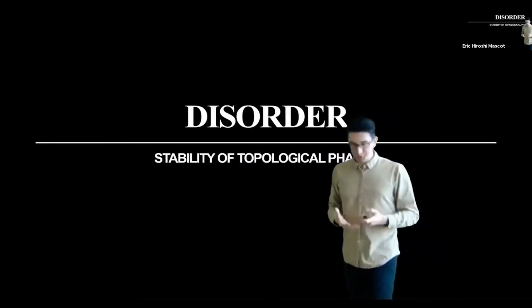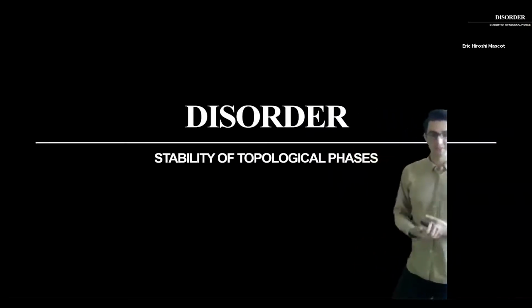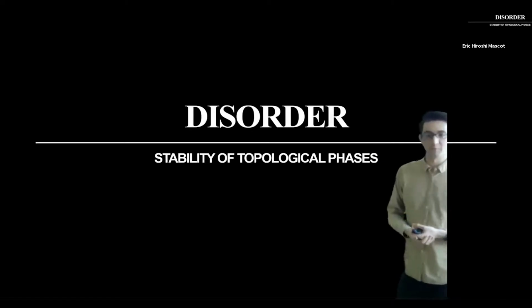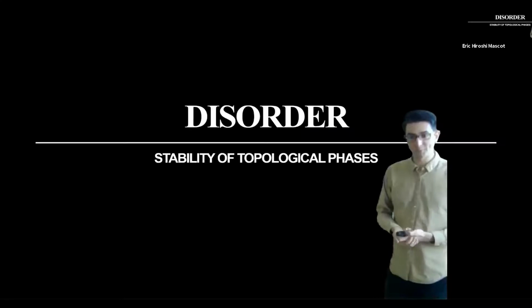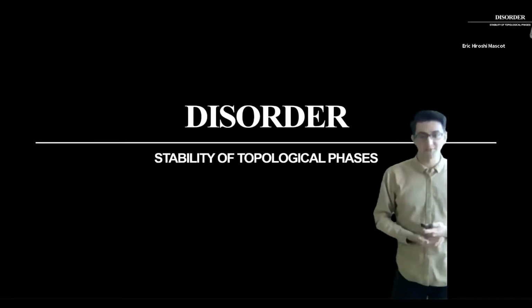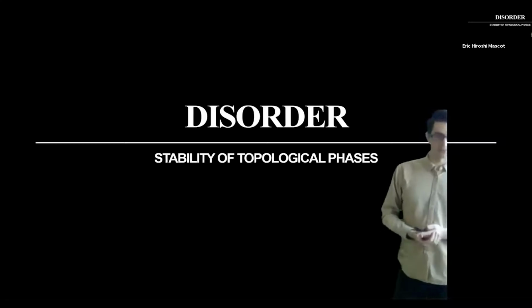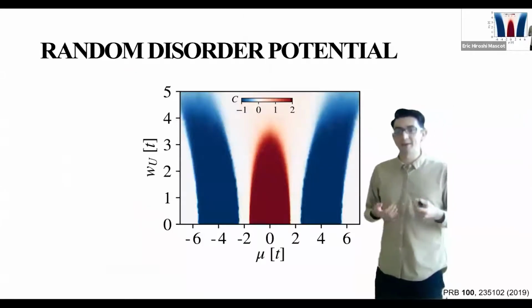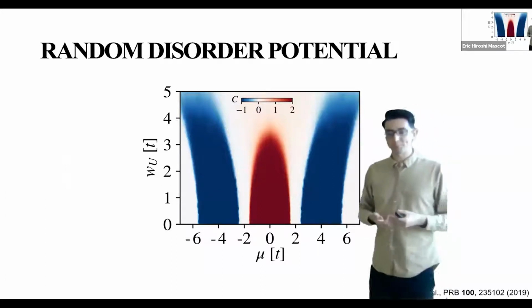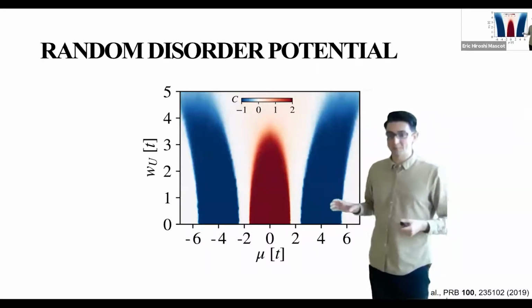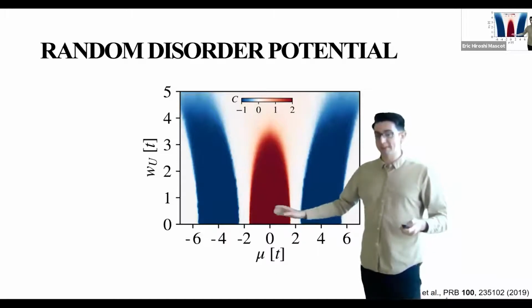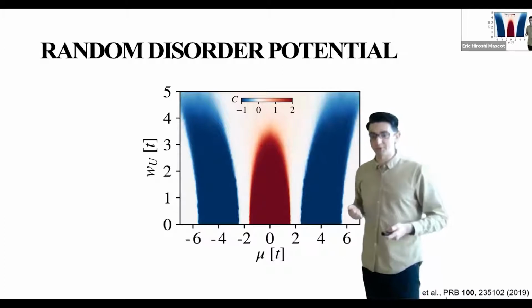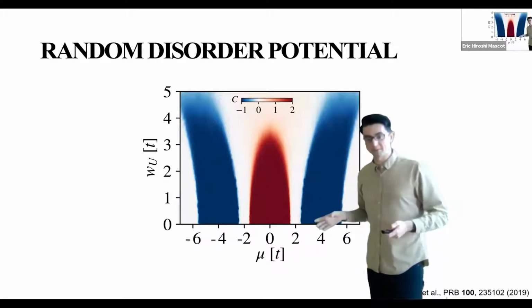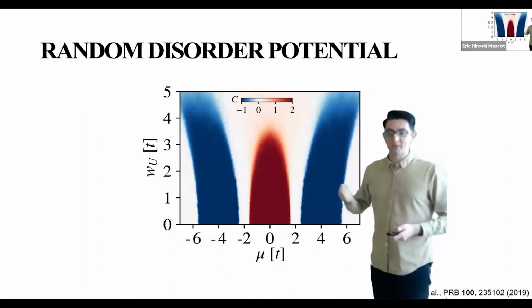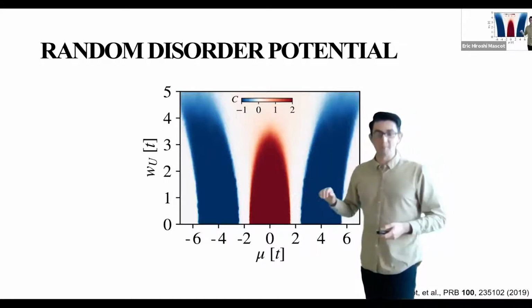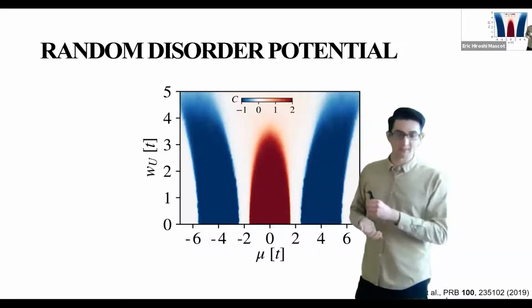Okay, to use these topological superconductors in devices, we want to make sure that these will be strong, robust against disorder. And so we looked at the stability of the topological phase in these topological superconductors. So here we look at random disorder. And we have this phase diagram where we have these topological phases. And as we increase the strength of the disorder, we see that these topological phases persist up to very large disorder strengths, which are many times larger than the superconducting gap size.